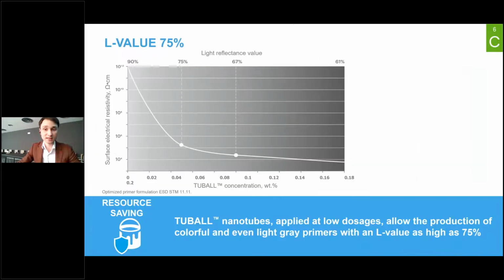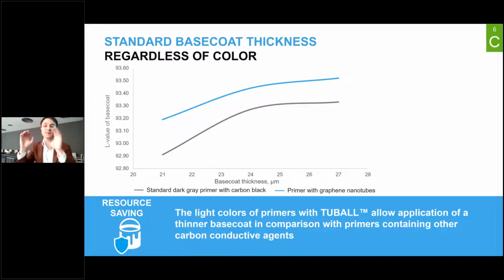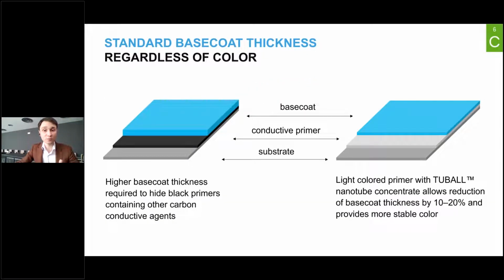In this application, single wall carbon nanotubes also give the ability to produce colored primers. On the slide, you can see the dependence of resistivity on dosage, and also possible colors which you can achieve. At the main working dosages of TUBALL, you can reach an L value between 67 and 75%, which is a very nice level. And this is extremely important, because if we apply the same thickness of the base coat on samples, on the same substrates which were painted with black primer and with a light gray primer, we will see differences in the final L value. And this is important because we can decrease the consumption of base coat and reduce the costs for the overall formulation.